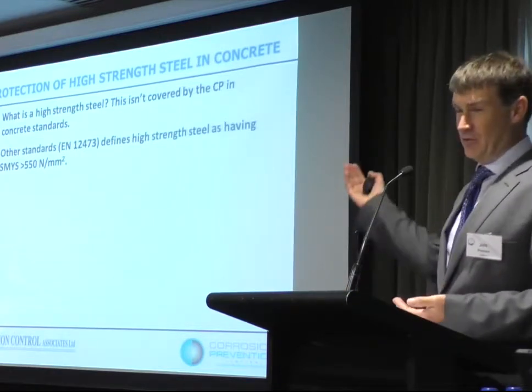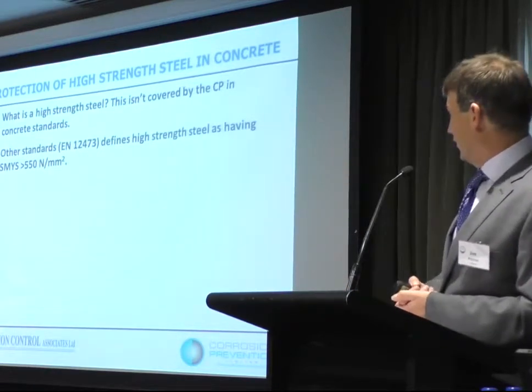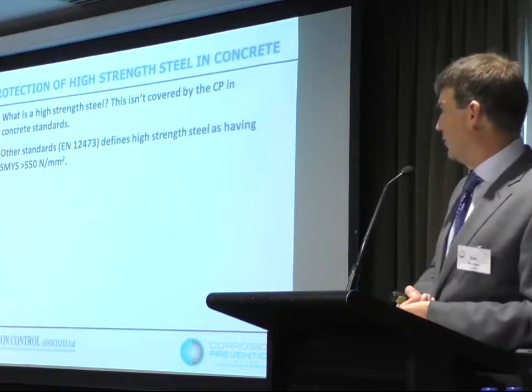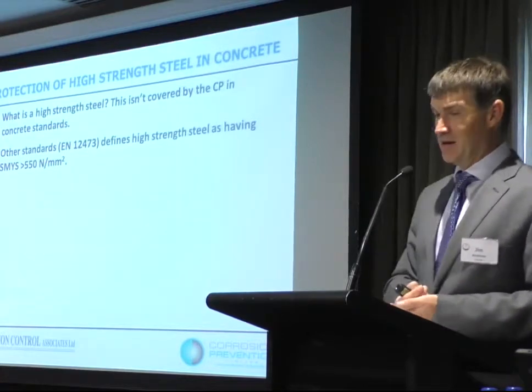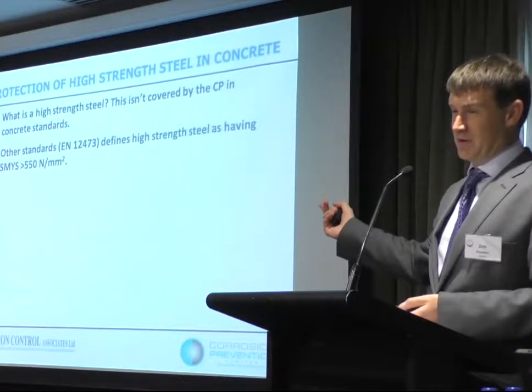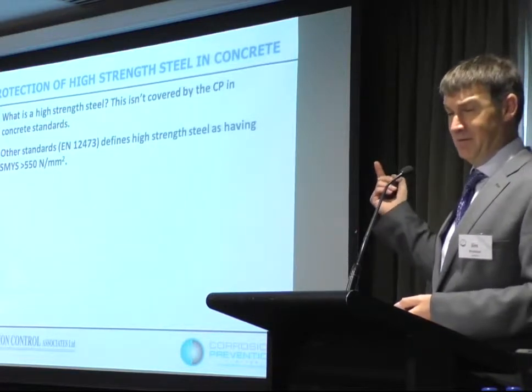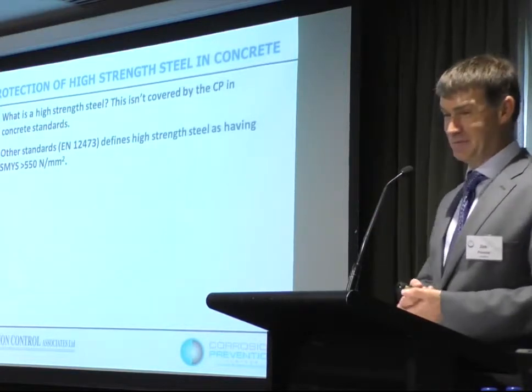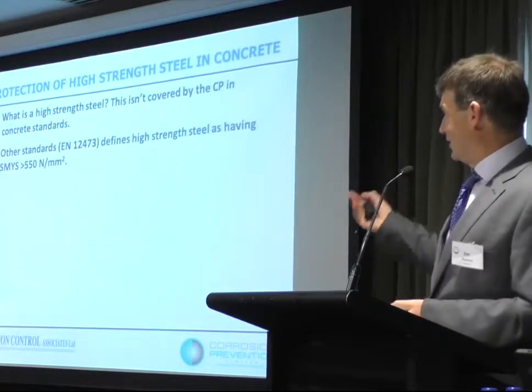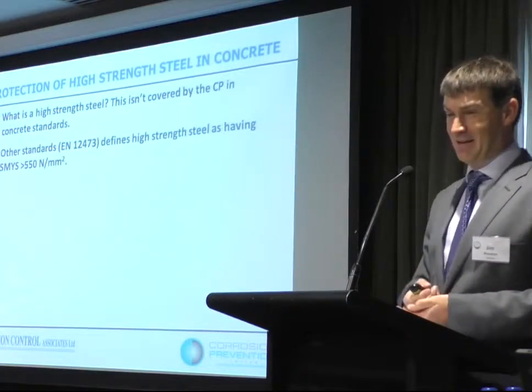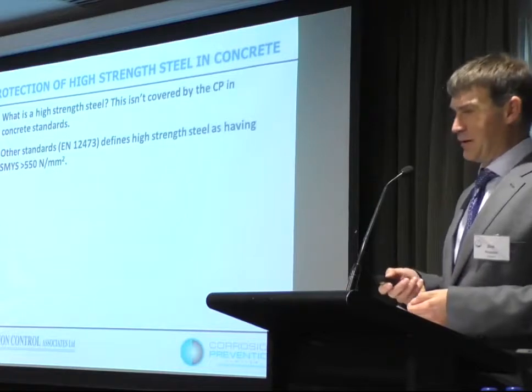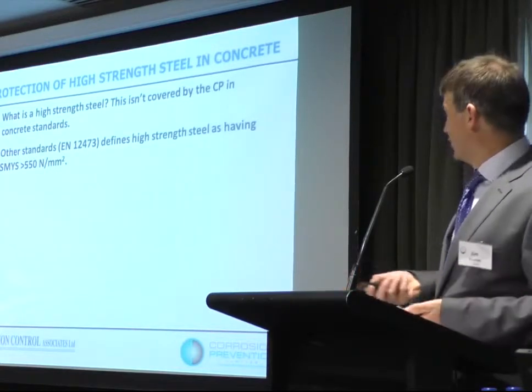Other standards, such as the general principles one for seawater, define a high-strength steel as having a specified minimum yield strength greater than 550 newtons per millimetre squared. The previous version of that standard had a much bigger number in terms of specified minimum yield strength. Some other standards define it by hardness, in terms of trying to align that to strength. So what is a high-strength steel?